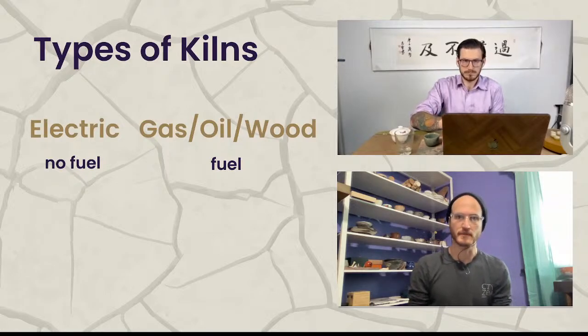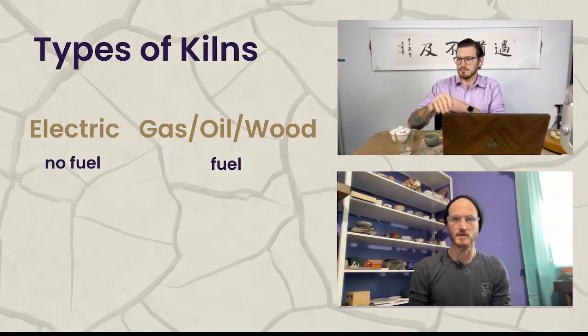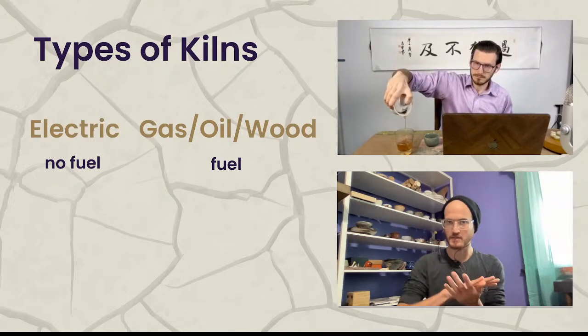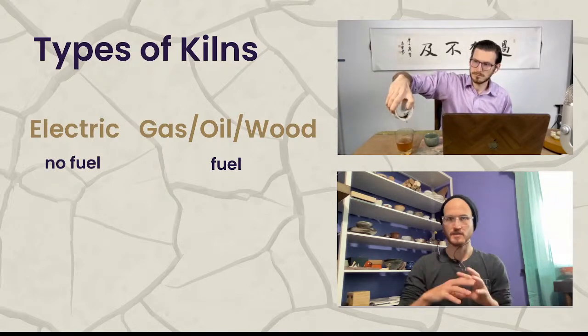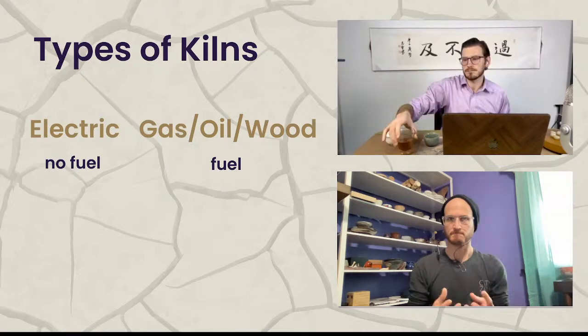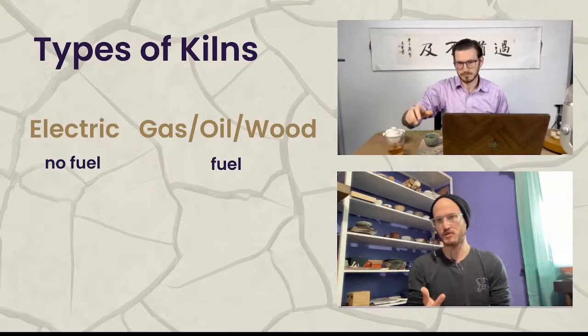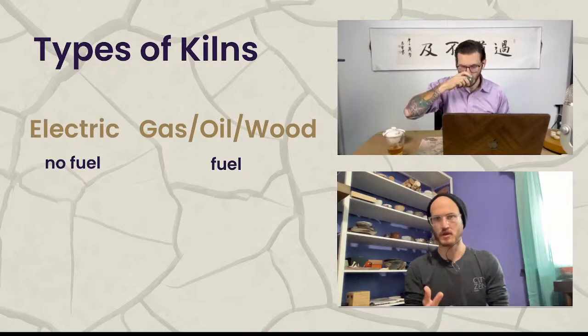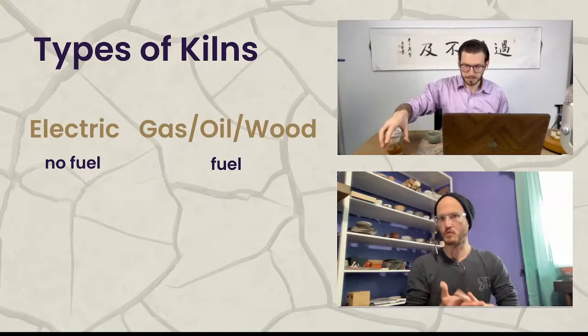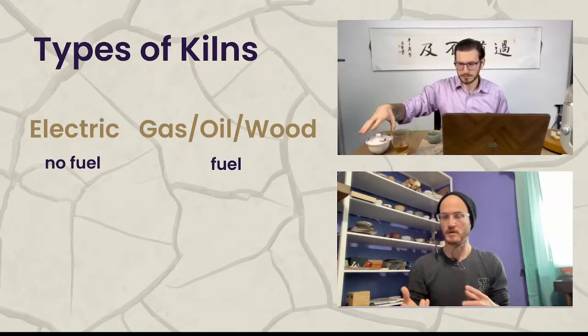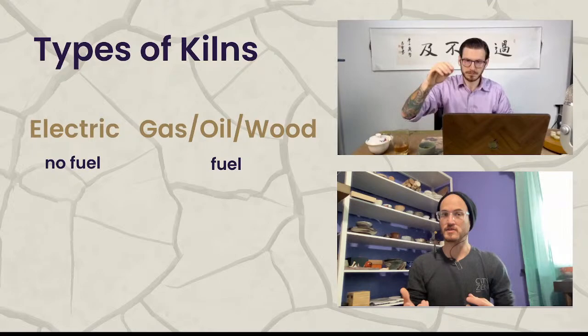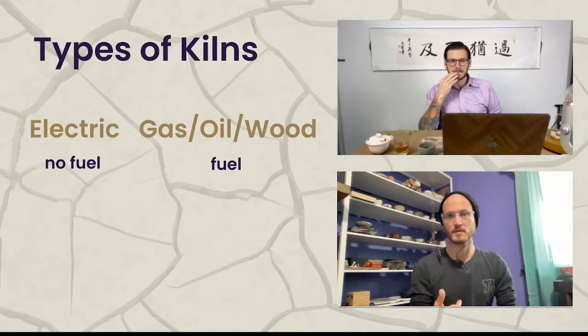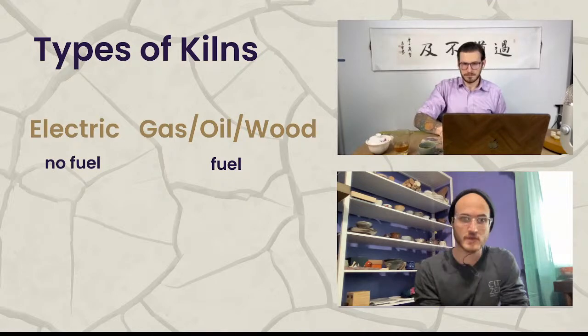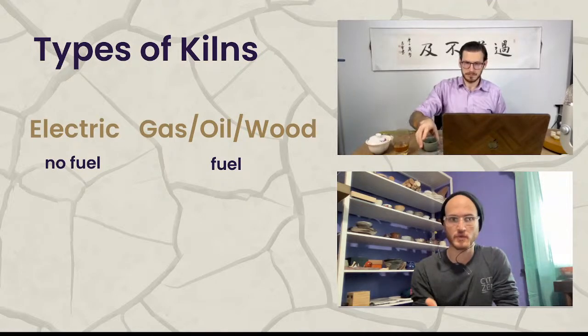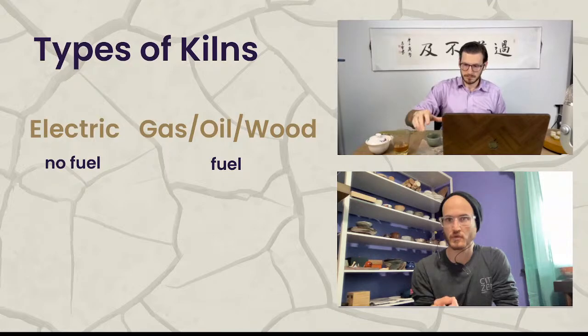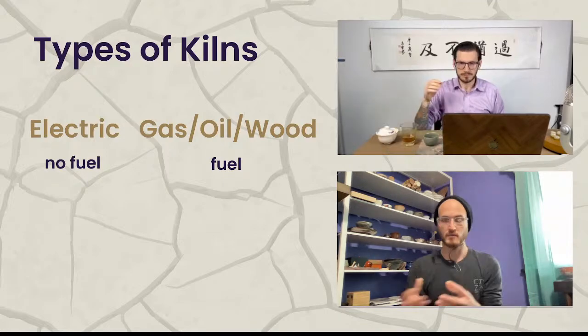And mostly those are used for bisque firings. So if you fire your pots first time, it basically makes them safe to glaze and gets out any organic materials. And then you can fire them a second time with glaze on them, and that's where you get a choice between oxidation or reduction, or just what kind of kiln you want to fire them in, because you can do pretty much anything at this point. But there are certain reasons to fire in reduction, which we'll get to. So the way you fire in reduction is by using a fuel kiln. So a kiln that uses some combustible fuel, whether that's gas, oil, wood, coal, and you're introducing the flame with that fuel.